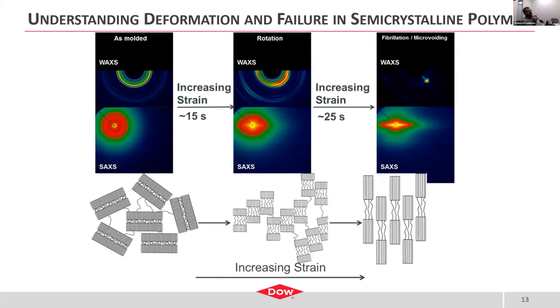So one thing that our team at Dow does to analyze these TPO-based materials is to understand the failure mechanism and the use of new additives into these materials to improve their properties. So to give you an idea, I wanted to show how we use small angle and wide angle X-ray scattering to understand deformation and failure in semicrystalline polymers. When we look at an as-molded or a compression-molded polyethylene part, we get a nice symmetric wide-angle X-ray scattering and small-angle X-ray scattering pattern. They're very isotropic. If you integrate the intensity as a function of azimuthal angle, you'll get very flat lines.